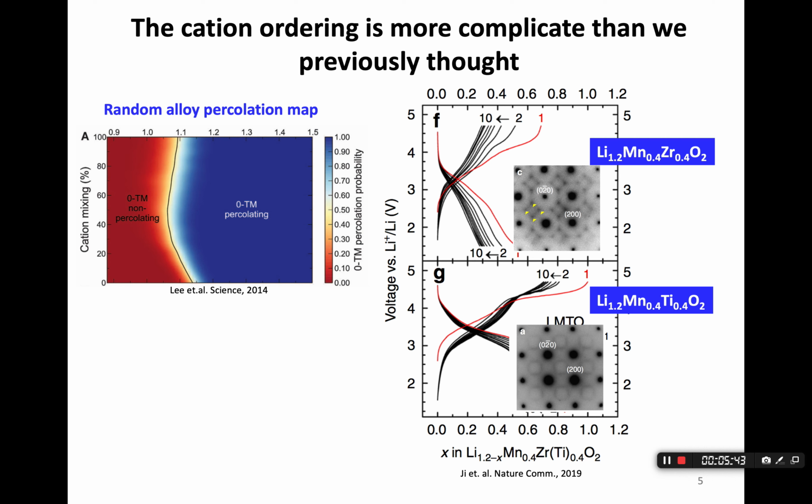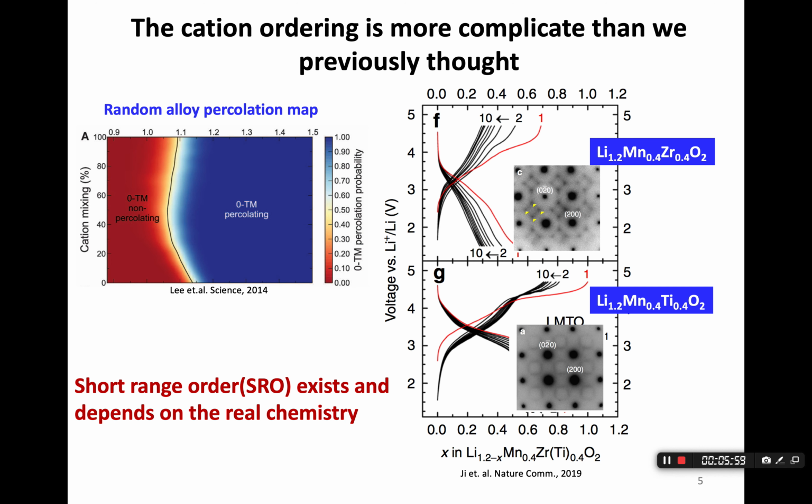And on the other hand, the LMTO have diffusive electron diffraction patterns, which look like a ring. So this is an indication of short-range order happening in these disordered solid solutions, which sort of rings the bell that short-range order is the key to manipulating the performance of the materials.